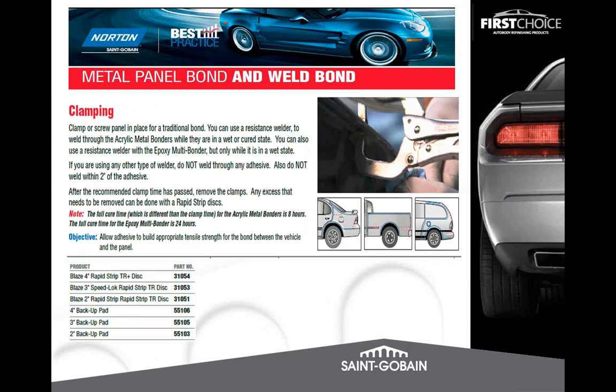Now, can I accelerate an epoxy? Sure. And the typical rule of thumb is for every 20 degrees I increase in temperature, I cut the time in half. So all glue cure times are based at 70 degrees Fahrenheit or 21 C for our friends in Canada, or that are used to Celsius. So if I'm in a, say, 90-degree day or a 90-degree shop, then my 24-hour cure time at 90 degrees, if it's panel temperature and it's constant, has now just been cut to 12. So you can accelerate the cure time with an epoxy, but the acrylics, no matter what the temperature is, 8 hours because it's just got to do what it's got to do.